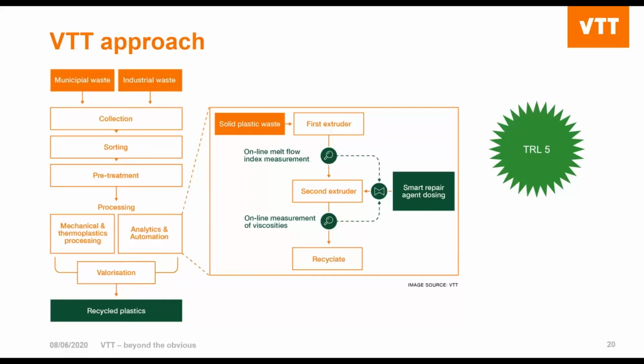First, we can feed virgin polymer to make up for the feedstock variations. This is already in use. Another approach is to feed compatibilizers to improve the mixing of different polymeric fractions. This is already in plan and will be realized soon. And to completely close the loop in terms of controlling the effects of degradation, we would like to also extend this technology in feeding chain repair agents to counteract the effect of degradation and repair the degraded polymer chains. This is at the moment still in the planning stage, but we believe that this approach will help us to achieve a better recyclate quality, a better recycling rate, and while we are improving sorting and separation, we are less dependent on ideal plastic fraction separation.